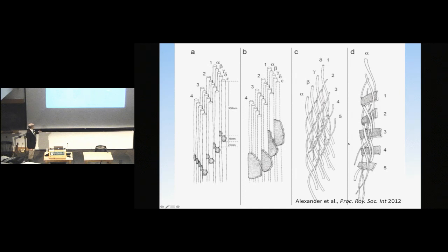And so what we found and then verified by TEM is that we think there's a structure that's more like this, where there are a few preferred directions that platelets of mineral, and this is again now compressed down by a factor of 30, can squeeze their ways between the ends of tropocollagen molecules. What's the dimension of these platelets? These are about 30 by 40 by 2 nanometers. This is the 30 direction, this is 40, and then going into the plane here is 2. And I'll show a video that makes this clear in a second, so I won't continue with that.